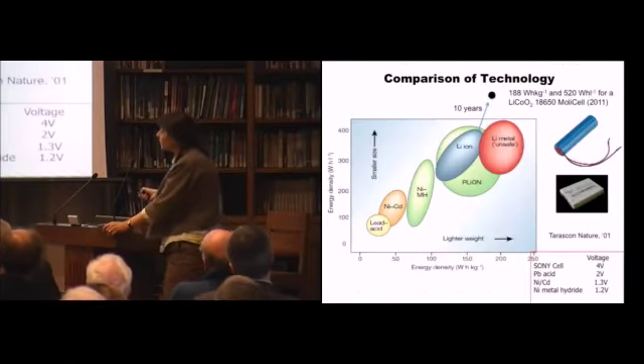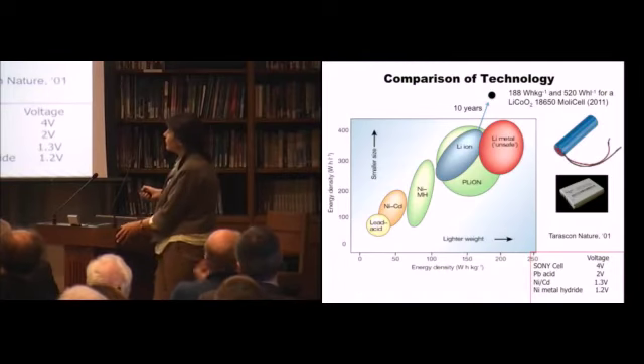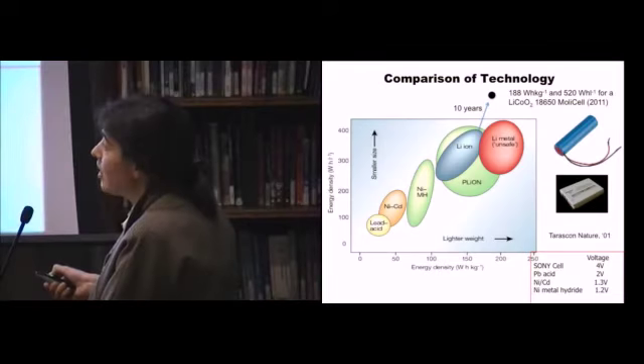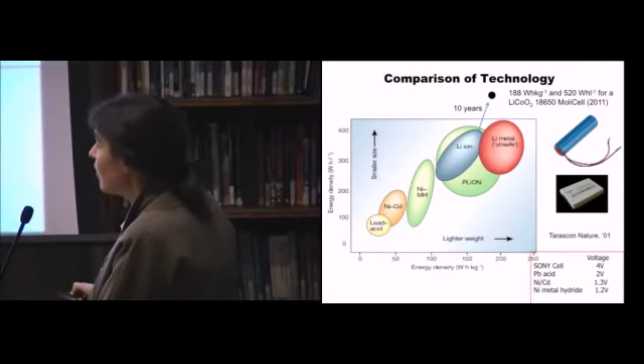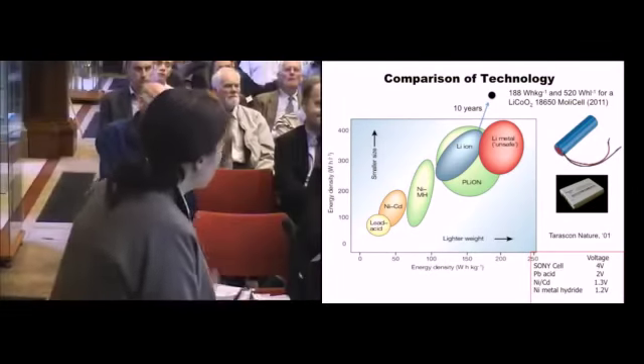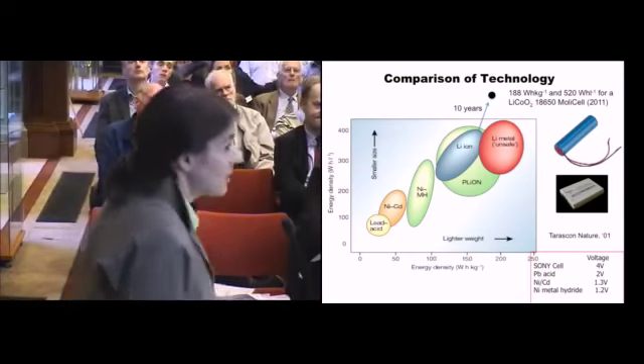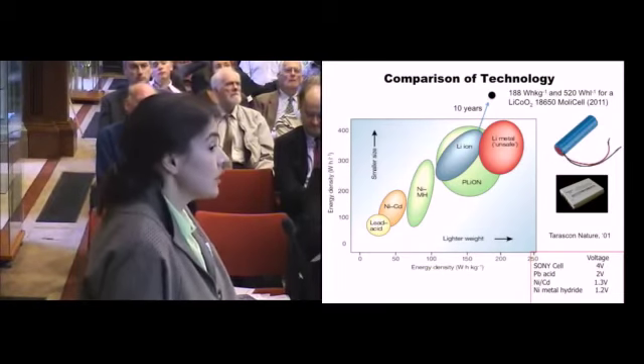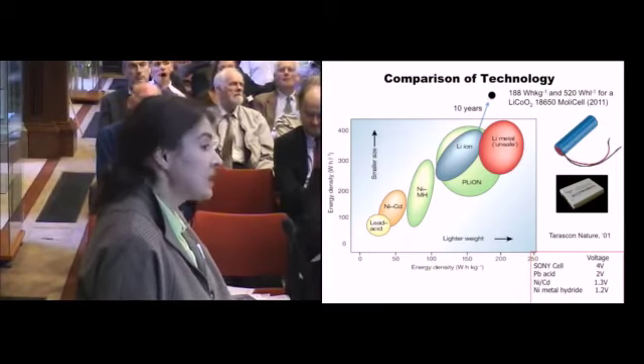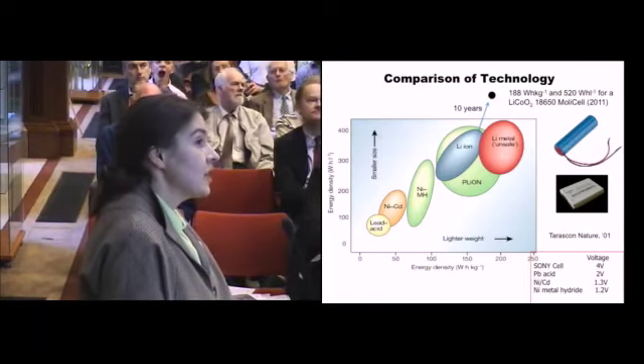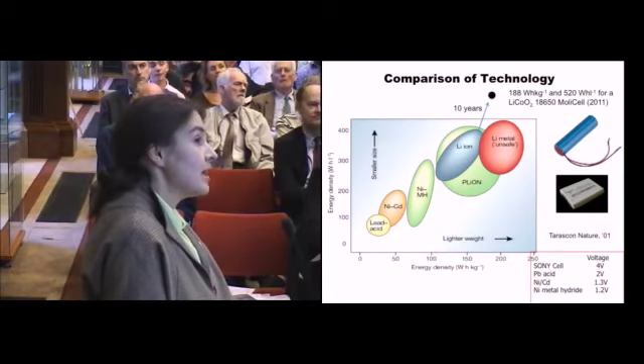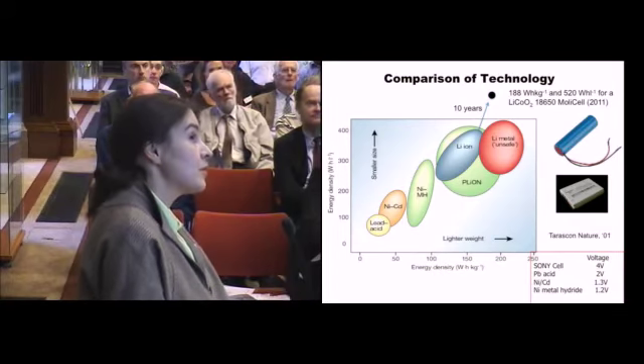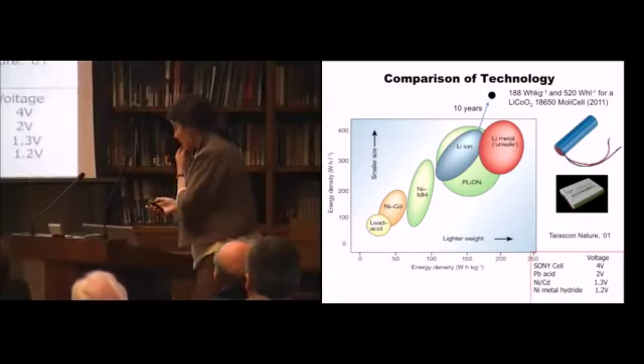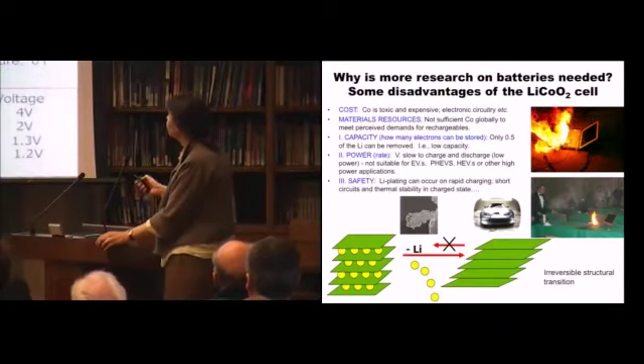So this is now the energy technology in 2001, comparing the energy density on either a volumetric basis or a weight basis. Depending on the application, sometimes the volumetric basis is more important than the weight basis. So here's lead acid going all the way up to lithium-ion 10 years ago, and through incremental improvements for the same chemistry, we've now increased the capacity noticeably in the last few years.